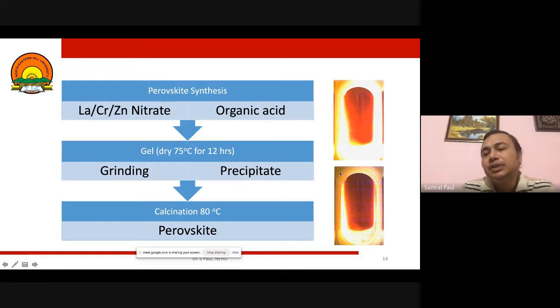It is very low. Here we have used microwave reactors to understand how the reaction takes place, and in the microwave reactor, we have put a camera to see how the reaction is taking place. The use of microwave is very good for synthesis, for two reasons. One is that you can synthesize the particles or whatever substance at very low temperature. Normally perovskites are synthesized at 120, or if I want to synthesize titanium dioxide, I have to calcine it at 600 or 800. Instead of that, we can just do it at 60 to 70 degrees centigrade.